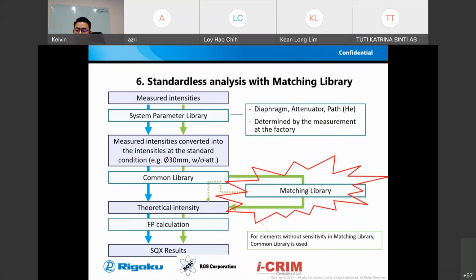This matching library allows you to put in a so-called standard. Of course, this standard is not enough to form a calibration curve. When we talk about a calibration curve, the minimum standard we need is at least 3 and above, to give you a logical calibration curve. But a lot of times, especially in universities and research institutes, they don't have the luxury of a lot of different standards because everybody is doing different things. It doesn't make sense. So if you already have one or two known samples, you can make them a standard and put them in as a matching library.